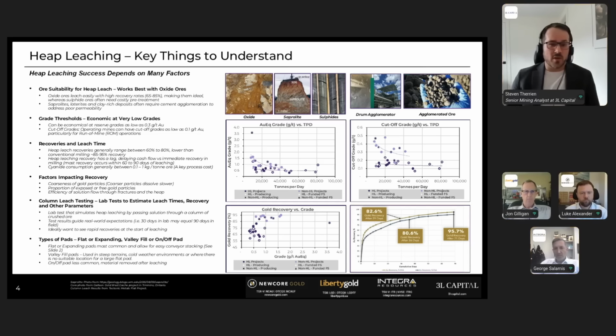Gold grades as low as 0.2 to 0.3 grams per ton can be economical across different throughputs, and cutoff grades at heap leach mines can reach as low as 0.07 grams per ton for run-of-mine heap leach operations. The recoveries, like I said, usually range between 60 to 85%, and that's lower than what you'd see with a mill, which is, I would say, between 85 to 95%. And unlike milling, where recovery is immediate, heap leaching recovery does have a lag, and there's some delayed cash flow there.